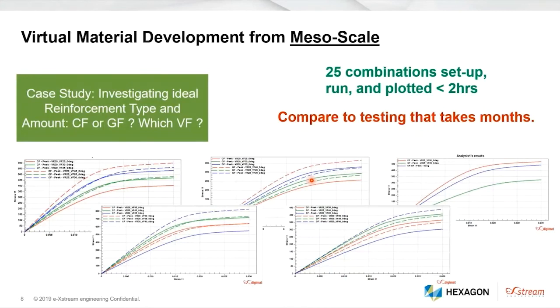The second case study for virtual material development from the mesoscale is investigating the ideal reinforcement type and amount. So the question here for the designer is whether to use carbon fibers or glass fibers, and then with which amount of volume fraction. With this activity, we can compare 25 combinations and setups, run them, and plot the results in less than 2 hours. When we compare such an activity with physical material development, the latter can take up to months to perform such a study.